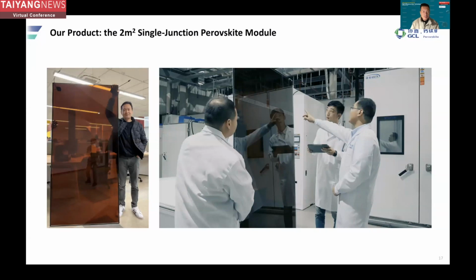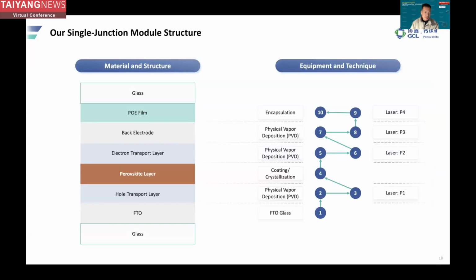This is our 1x2 meter module, and it is 2 square meters large, and is taller than me. In the production procedure, we deposit a hole transport layer, and then perovskite and an electron transport layer, and then back contact, and then a POE film for the encapsulation. And here, only the perovskite layer is coated by slot coating. All the other layers are deposited by PVD. So we can use a lot of PVD technology from the display panel industry, and also from the semiconductor industry, and also from our partners in the silicon industry. And we can see that our modularization is formed by laser P1, P2, P3, and P4. That's typical for thin film PV modules.